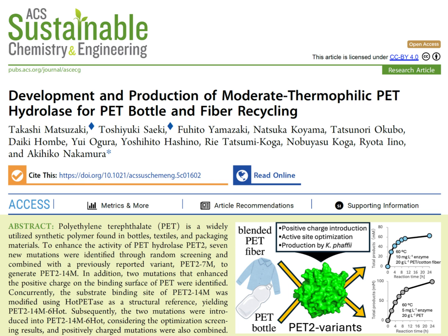They did. And the results were quite telling. For pure PET fiber and also for PET cotton blended fiber. A really common blend. Yeah. PET2-14M-6Hot actually performed better at 60 degrees Celsius than LCC-ICCG did at the higher 70 degrees Celsius. Better at a lower temperature again. Yes. And what's really fascinating about the PET cotton results is they clearly suggest the enzymes selectively degraded only the PET. That cotton fibers were left intact.